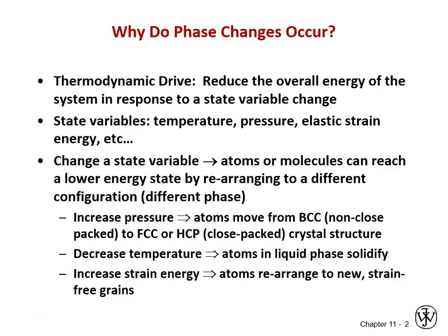Obviously, if you decrease temperature, things will tend to want to solidify from a liquid. If you increase strain energy by cold working something tremendously, a huge reduction in area in a single pass, say at temperatures below recrystallization, you're going to encourage the atoms to rearrange into new strain-free grains, which of course is the drive for recrystallization, which we saw in our strengthening chapter.